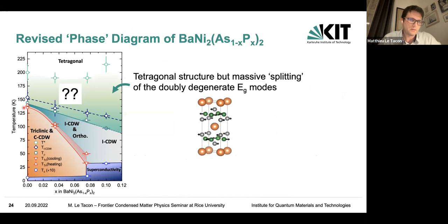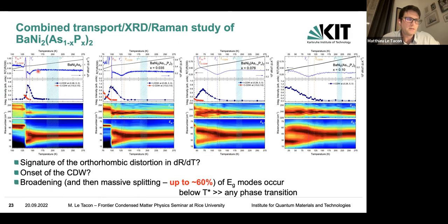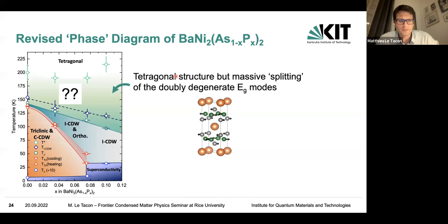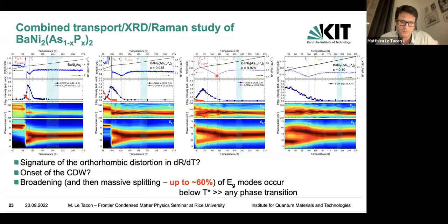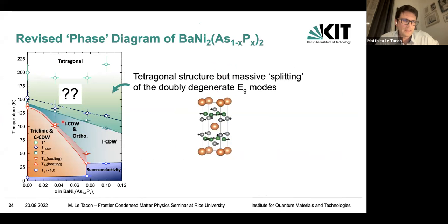So we nicely see where the tricritical transition is taking place. We measure superconductivity; Christine Villa did that with specific heat. So nicely the superconducting state. We do have then the signature, we thought, at least, of the orthorhombic distortion, maybe in the resistivity, and there was a kind of minimum in the resistivity, which, at least in the parent compound and at low doping, seems to be well aligned with the thermal expansion. It's a bit different at higher doping, but if there is an atomic distortion here, it's actually below the minimum of the resistivity derivative. So anyway, the bottom line is that this onset of the broadening of the phonon is occurring at much higher temperature.